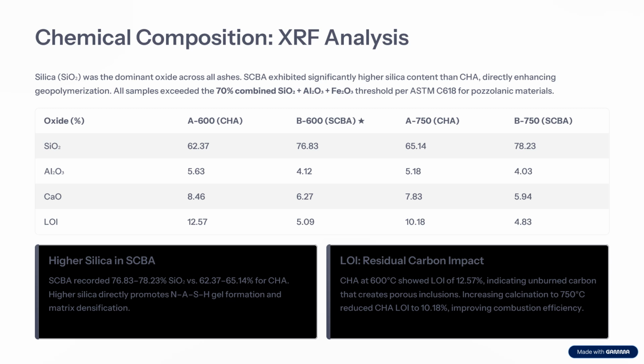For the chemical composition, XRF shows that silica was the dominant oxide across all ashes, and SCBA exhibits significantly higher silica content than CHA, directly enhancing geopolymerization. All samples exceeded the 70% combined SiO2 plus Al2O3 plus Fe2O3 threshold per ASTM C618 for pozzolanic material. For example, for the oxides at A600, SiO2 is around 62.37, Al2O3 around 5, CaO around 8, and LOI at 12.57.